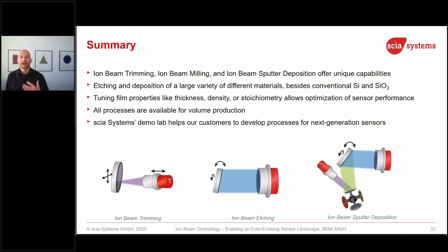So in summary, the ion beam trimming, milling, and sputtering offer some unique capabilities if it's about etching or deposition of various materials, besides this conventional silicon or silicon dioxide. Of course, it's not competing with RIE if you want to etch silicon or silicon dioxide. But we are able to tune film thickness, density, stoichiometry, and by that, our customers can tune and optimize the